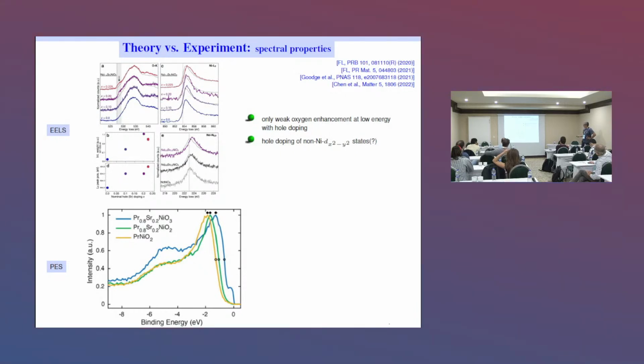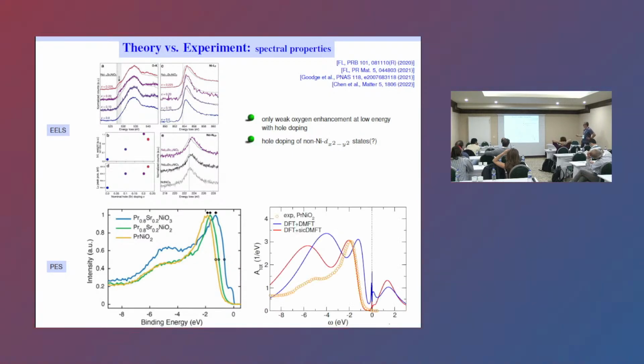This orange curve, you see the peak is at -2 of the nickel D, and then we have the oxygen peak at -5, -6. And that was in 2022, and my calculation was at 2020. So that is the comparison. I took over this curve. I just looked for the height of the peak, but then I put over the curves.